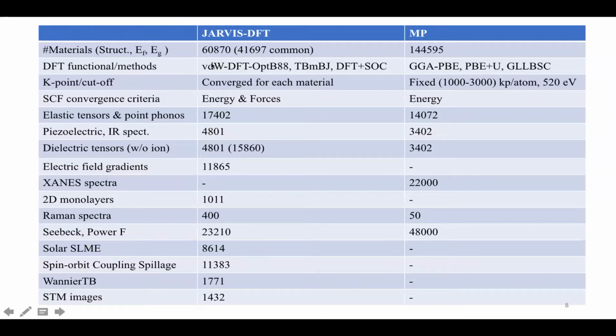Our JARVIS-DFT uses the van der Waals DFT OptB88vdW functional, the Tran-Blaha modified Becke-Johnson, and DFT plus spin-orbit coupling cases. And we converged the k-point and cutoff for each material, and we converged on the energy and forces. So these are some of the key differences with Materials Project. Materials Project has more than 2 times the number of materials, but having such convergence and more properties per material tends to make our database a little bit smaller than bigger databases with millions of materials and so on. Currently, we have elastic tensors for around 17,000 materials, and we have gamma point phonons.